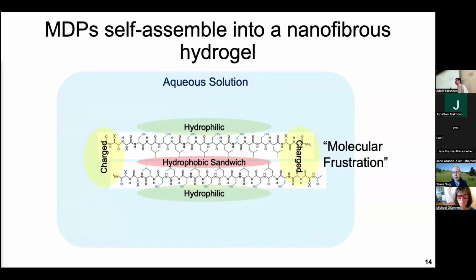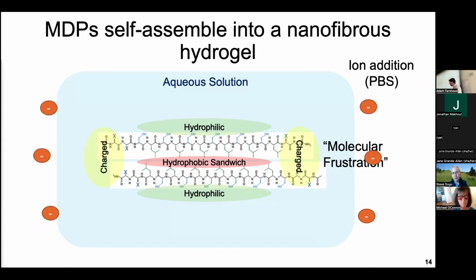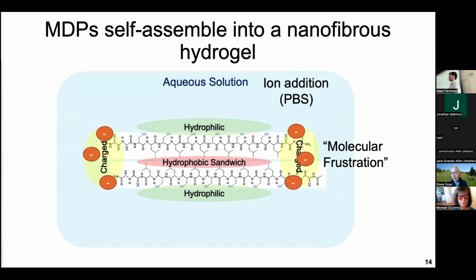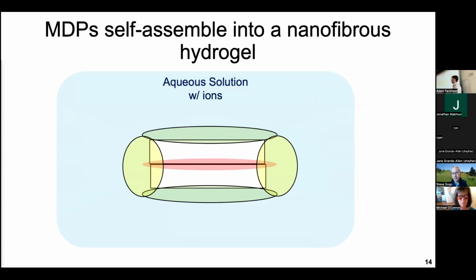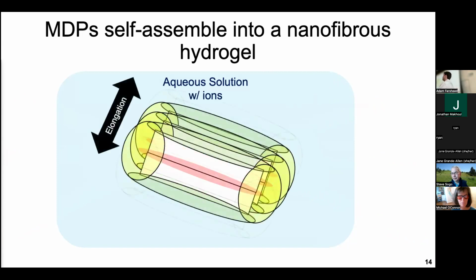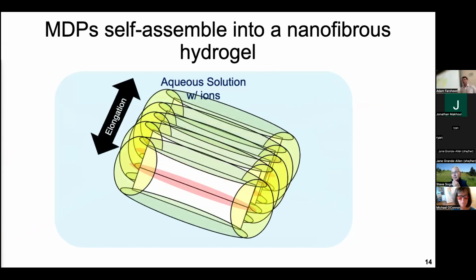But when that occurs, you're going to have this kind of counteracting thing occurring, which we call molecular frustration, that happens at the termini. Whereas if you have the same charge in close proximity, the molecule is not going to be very happy, and it's not going to want to maintain the structure. But if you then add ions, similar to what's in our body in physiological solution, those ions are able to quench this molecular frustration, and we get this nice elongation of these fibers.